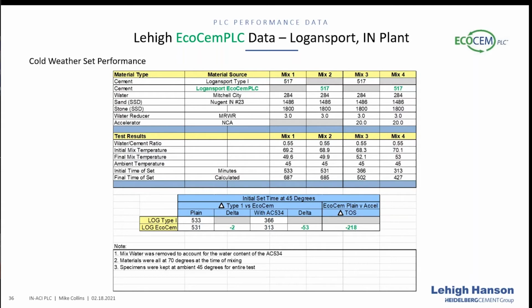We set the room down at 45 degrees and did some mixes, looking at what would be an everyday, maybe interior slab mix, and ran the time of set at cold temperatures. Essentially what we found is that the PLC from Logansport set 2 minutes quicker than the equivalent Type 1. With the addition of a non-chloride accelerator, it set almost an hour quicker, 53 minutes. And from the plain Portland limestone cement to the accelerated limestone cement, there was a 218 minute difference.